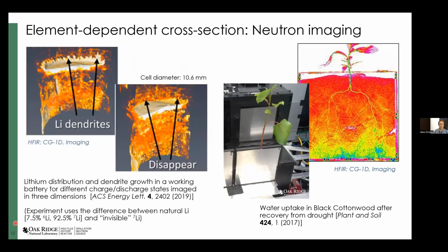Because you can see lithium very well, you can put a working battery on a neutron imaging beam line, and you can cycle the battery, you can charge and discharge the battery, and you can watch how these fingers, these dendrites, grow. These are the ones that result in short circuit in a battery. They're very detrimental. Usually they are studied by cycling a battery till it fails and then taking it apart and looking at where the dendrites formed. With neutron imaging, we can actually look at this happening while we charge and discharge the battery.